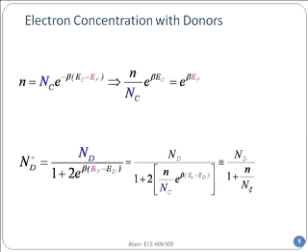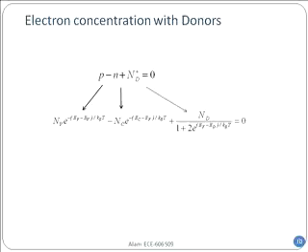So I will write everything that is known already in N sub xi. Now, of course, this is a material dependent constant. For silicon, it will be one N sub xi. For germanium, it is a different N sub xi. And the effective quantum mechanics and everything is hiding through N sub c. Effective density of states has effective mass, right? Effective mass knows about quantum mechanics. So all those are hiding in this little N sub xi. Okay, so from here, I can calculate.